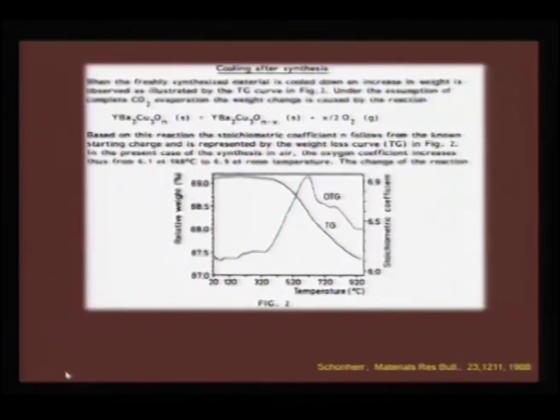Now, one more thing we need to understand, if you do a TG and DTG, you would find out that it loses oxygen when you heat up to 920 degrees, and therefore, a freshly synthesized sample at 920, when it is cooled down to room temperature, it will actually be a non-stoichiometric compound with oxygen value ranging from 6.8 to 6.9. So, YBa2Cu3O 6.8 to 6.9 is very critical for the superconducting phase to occur.